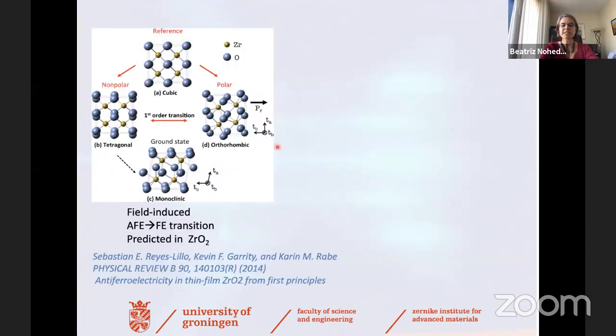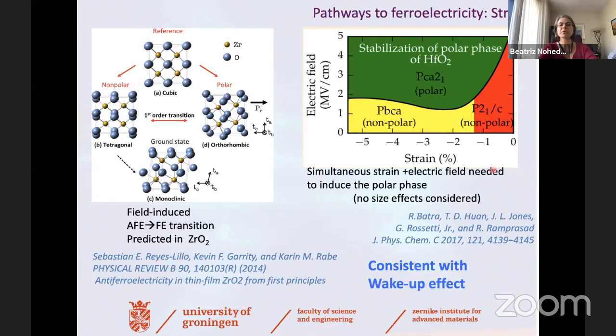Okay. So it's interesting because, as I said, zirconia is not ferroelectric, but you can stabilize it in a tetragonal phase, which is antipolar, antiferroelectric, and you can induce from pure zirconia the polar phase by applying an electric field through a first order phase transition. And this was first proposed by first principles calculations in this paper here. So it is possible to induce the ferroelectric phase from an antiferroelectric phase by applying an electric field. It is also possible, according to calculations, to induce the polar phase even without considering size effects, by applying enough strain to the material and an electric field. A combination of both of them can induce the ferroelectric phase even in large enough materials, according to the calculations.